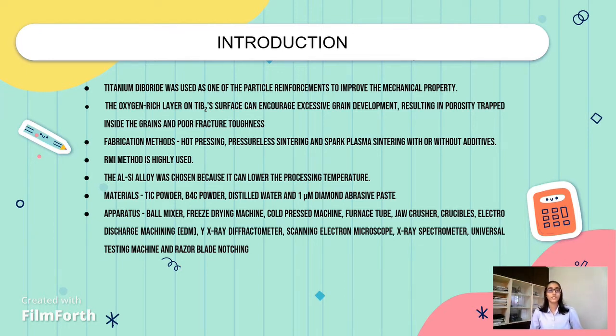The aluminum silicon alloy was chosen because it can lower the processing temperature, which is crucial for reducing thermal residual stress. Furthermore, as compared to pure silicon melt additions, the inclusion of ductile aluminum can improve the fracture toughness of silicon carbide ceramic composite. The composition of the preform and alloy melt may be adjusted to get the desired composition of silicon carbide ceramic composite.